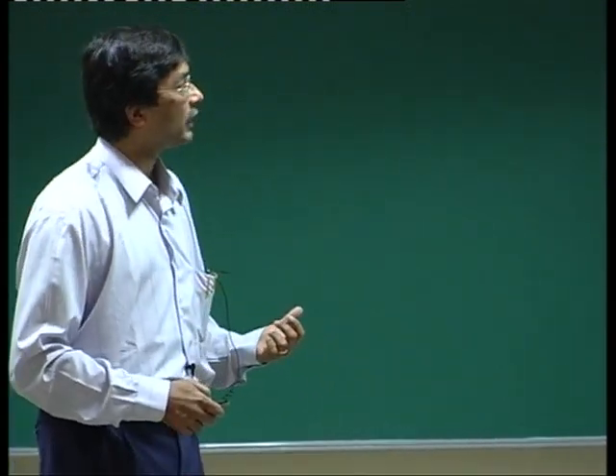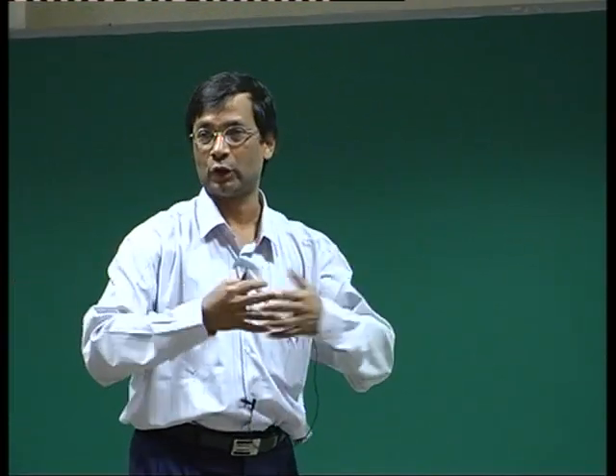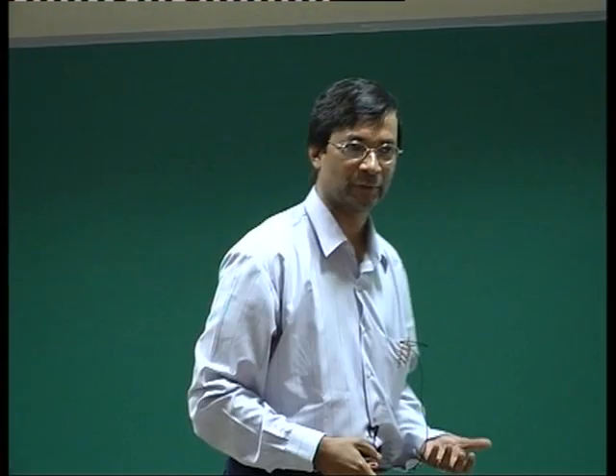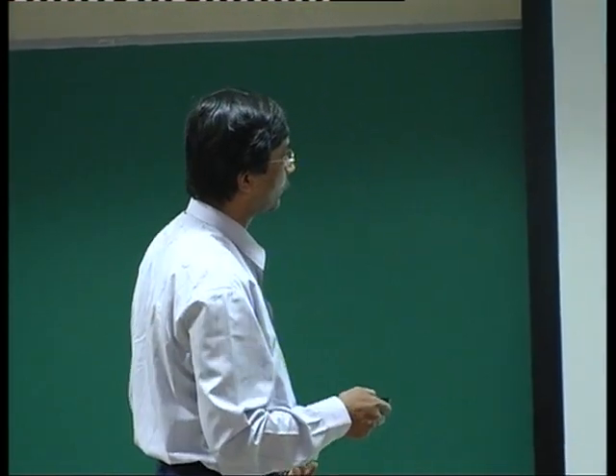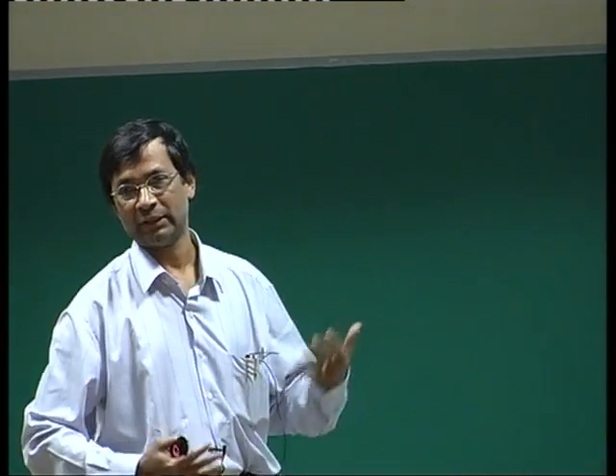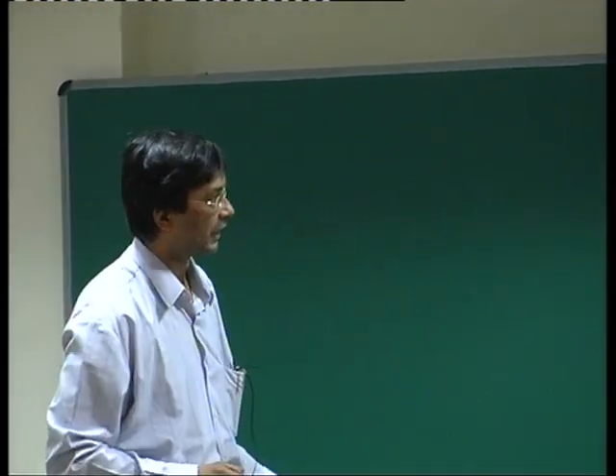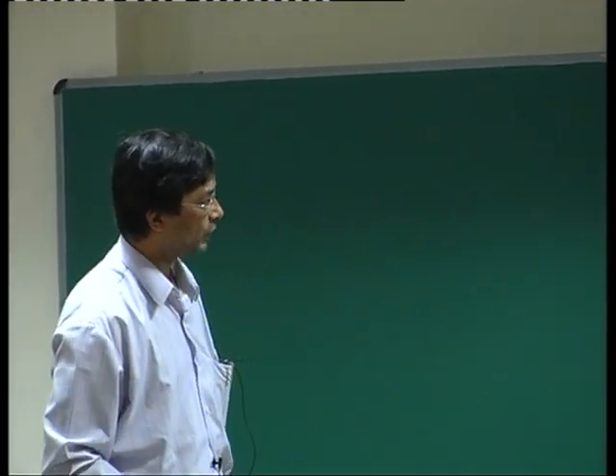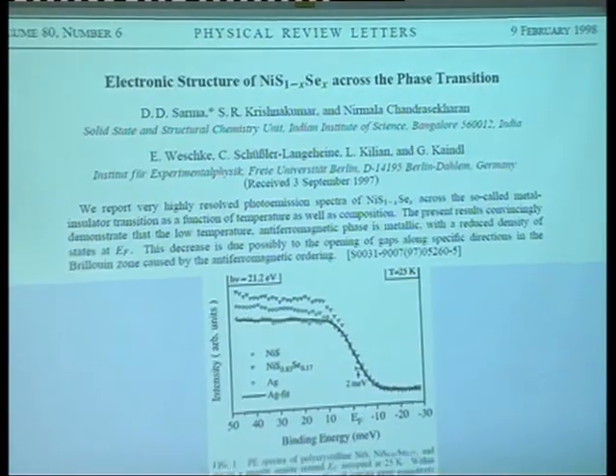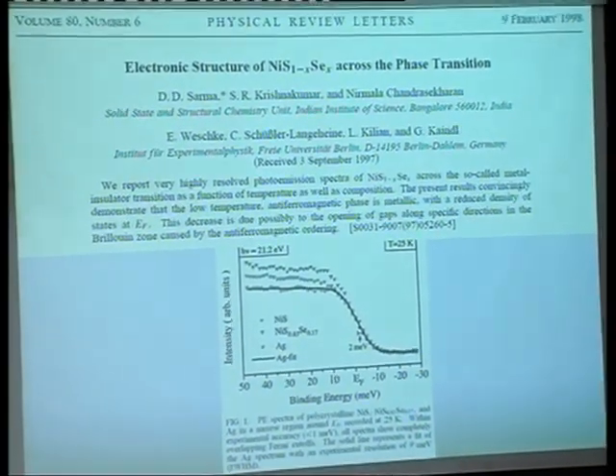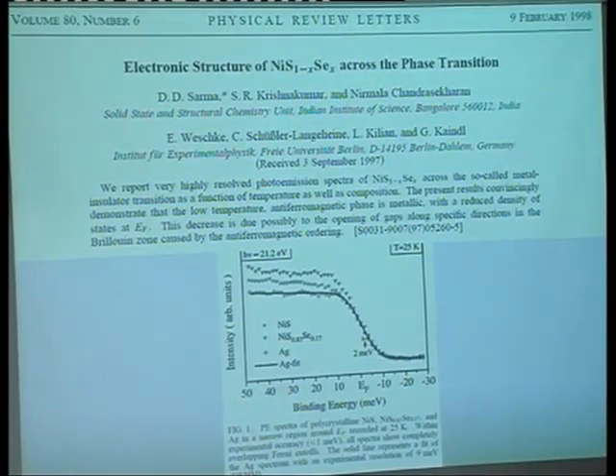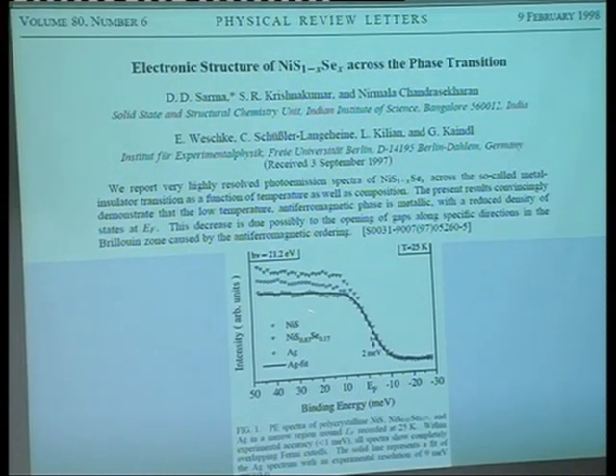So about 4 years later or 5 years later, by the theorem that I told you that every 5 years somebody comes along, so we came along and looked at it with somewhat higher resolution than was available to Professor Fujimori at that time. And what we found is shown over here, first of all. So I'm showing you 3 different spectra. And now, mind you, this entire stretch is 80 millivolts, not 450 millivolts that Fujimori's data was. It's 80 millivolts, the whole thing.